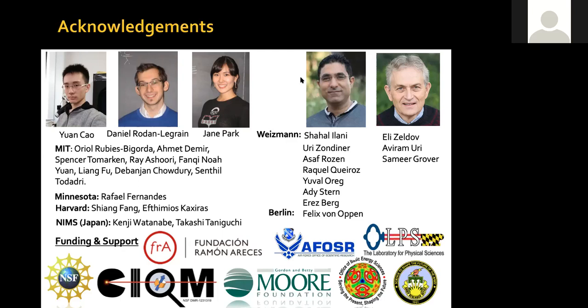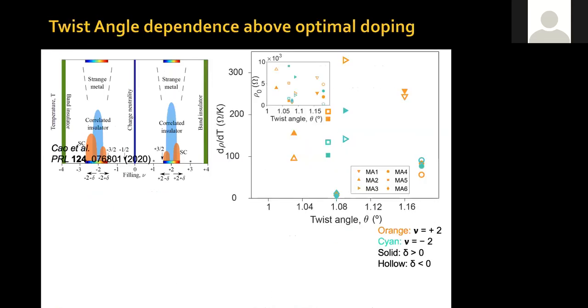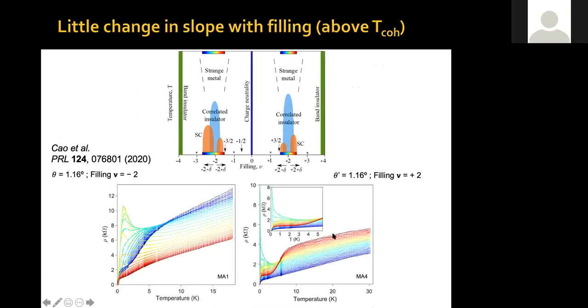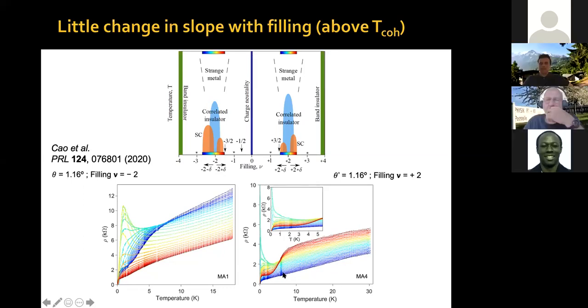Very good observation. So let me see if I can go back. Yes, as you can see, within this range in density spanning the insulative behavior and the superconducting domes on either side, the slope of the linear T resistivity is pretty much the same. What changes a lot is the offset, okay? The extrapolation to zero temperature, so the residual resistivity at zero temperature when you extrapolate the linear behavior. This is something that we have observed now in many devices. I'm showing here two devices, but we have many devices. We do not know exactly why this is the case.